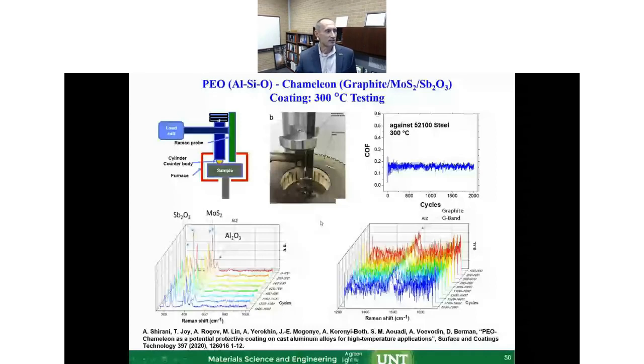Most recently, and now we're showing the result from my lab here at the University of North Texas, where we have this in-situ Raman tool, which was developed originally in the Air Force Research Lab, and now it's been reconstructed at UNT. And it's a very unique tool again. You can see here, you're looking right inside of this oven where all the action is. And this is the loading pin, and this is the Raman probe, which is taken out.